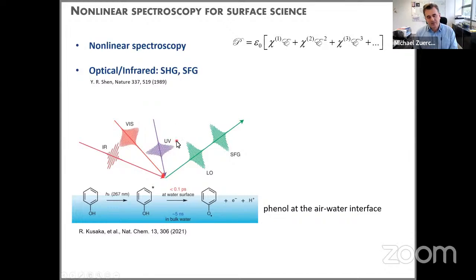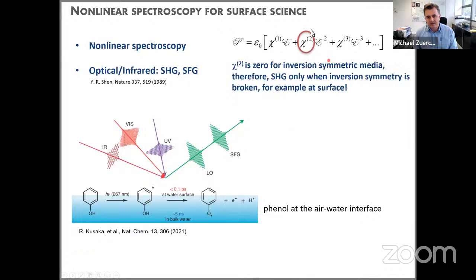The reason this is interesting for studying surfaces and interfaces, as shown, for example, here in this example of studying phenol at an air-water interface, is that this chi2 tensor, a rank 3 tensor that links the polarization with the second order of the electric field, is in fact 0 in an inversion symmetric medium. So all the tensor elements are 0 if there is inversion symmetry. Therefore, we can use second harmonic generation, or for that matter any of these second order responses, as a very sensitive probe of inversion symmetry.